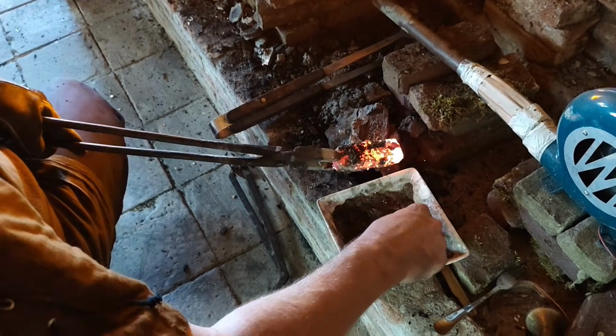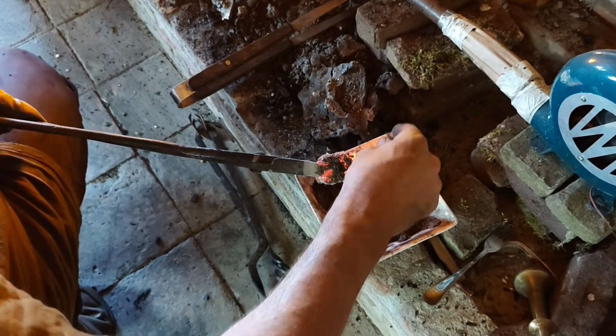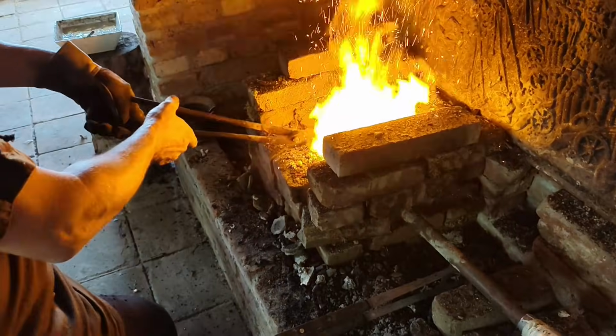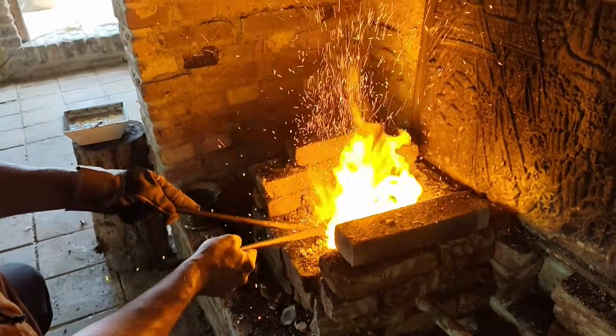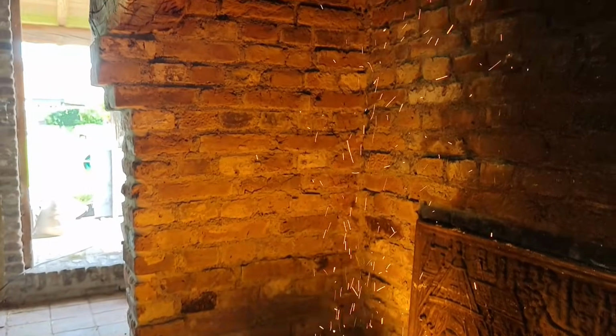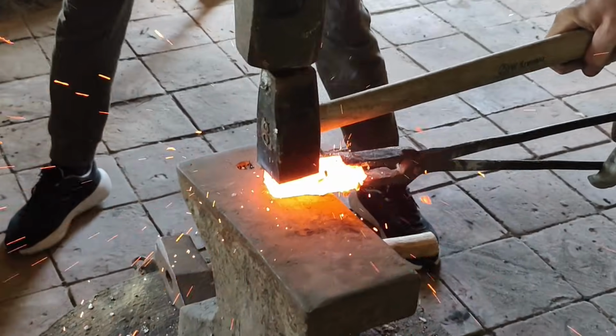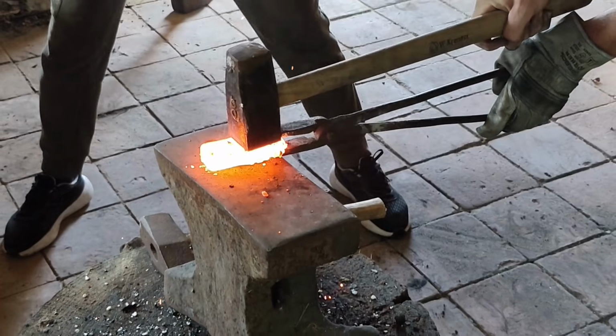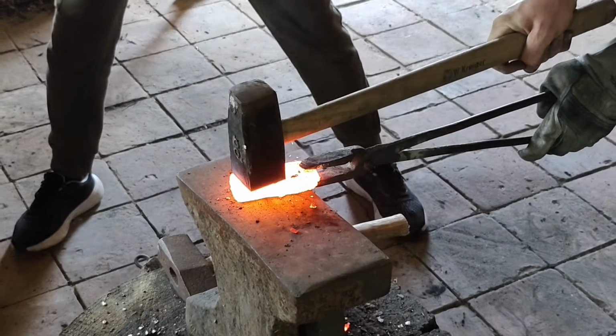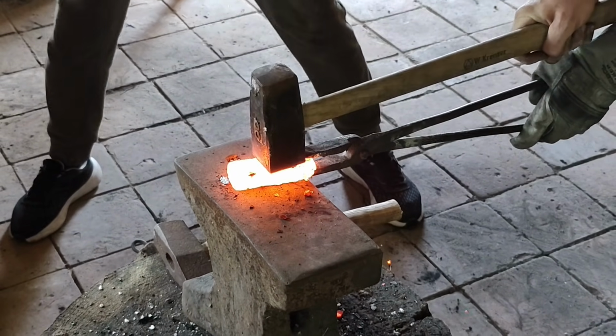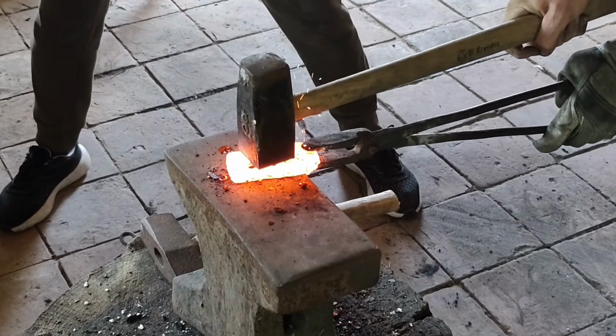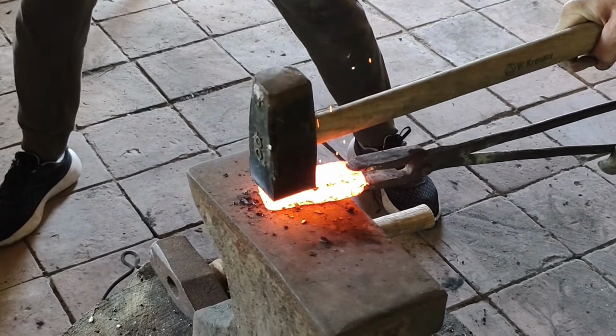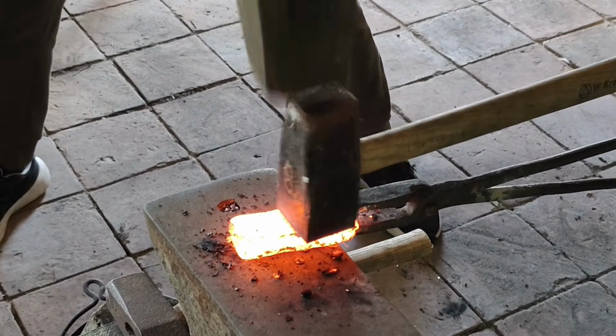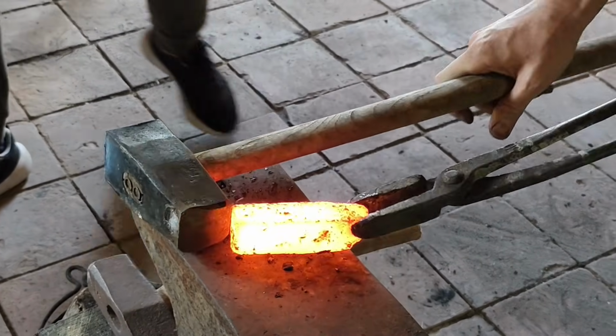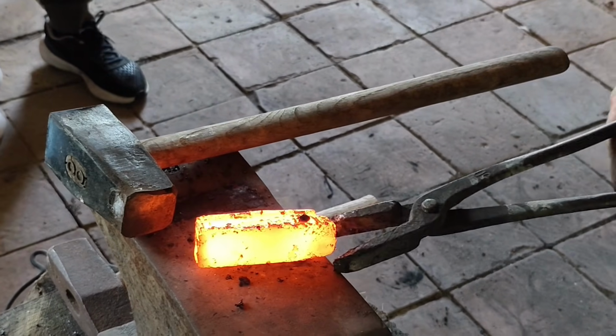Here we see the entire billet being forge welded into one complete homogeneous bar. It actually makes a lot of sense to construct the entire sword or sword blank out of multiple smaller bars, because individual smaller bars are much easier to refine with the right amount of heat and expel the slag content. Working with multiple thinner bars is much easier than when considering one big full chunk of steel.